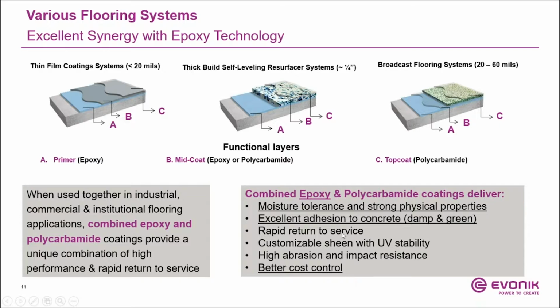Okay. Rapid return to service is important, as you mentioned, but a lot of times people don't want to use epoxy because they are slower. So here you pick epoxy technology that is fast cure. And then customizable sheen and UV stability, high abrasion and impact resistance is really brought in through use of polycarbamide technology. And by using the two technologies together, as you know, epoxy technology is a little lower cost, you're able to get better cost control of your whole system.